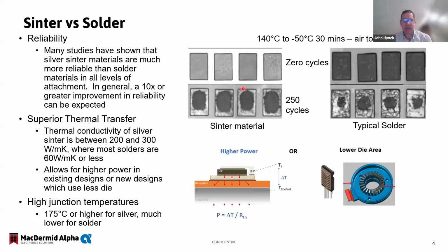in thermal cycling. And here we did a test of a sinter material and a solder material on a typical package attach application. We did a thermal shock test, or thermal stress test, from 140 C to negative 50 C, with a 30 minute dwell time in an air to air application. You can see at 0 cycles, very good CSAM results. At 250 cycles, you can see that the sinter material has pulled away from the edges a bit, but is still very much intact, where the solder material had pretty much hit end of life well before 250 cycles. So you can see in this test and many other tests that have been published that sinter materials are much more reliable than solder.